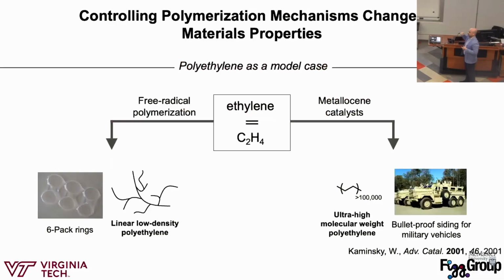The reason why I love controlled polymerizations is this is my favorite example of why it's so interesting and important. If we take ethylene, which is a very simple molecule, C2H4, and you do an uncontrolled polymerization, so a free radical polymerization of ethylene, you're going to get, this is a topology of the polymer structure, so this would be polyethylene. You're usually going to get this linear low density polyethylene with all of these branching points. And this is what we use for garbage bags, 6-pack rings, that's low density polyethylene. We all sort of know what that material property is like.